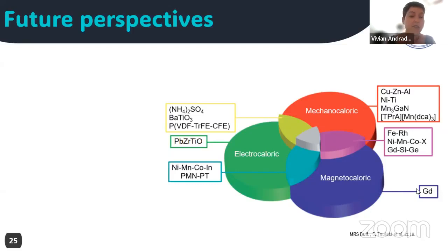In the case of gadolinium, since it's a second order phase transition, it does not break like the others. Gadolinium's adiabatic temperature change is around 10 Celsius degrees, and gadolinium-5 silicon-2 germanium-2 is around 20. But after several cycles, you have a reduction for the gadolinium-5 silicon-2 germanium-2, and for gadolinium you don't have that. So that's why it's the reference material.